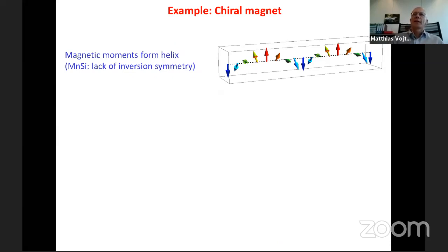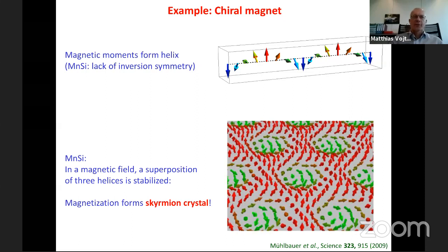Now, a somewhat more complicated example, still in the realm of symmetry breaking phases, are chiral magnets. This is where the magnetic moments, instead of being simply parallel, form a helical structure. This is shown in this picture here. And an important example is manganese silicide, which is almost a ferromagnet, but due to the lack of inversion symmetry in the crystal, the spins form this spiraling structure. Now, this is a conventional order parameter, but things can get even more complicated, or if you wish, more interesting.